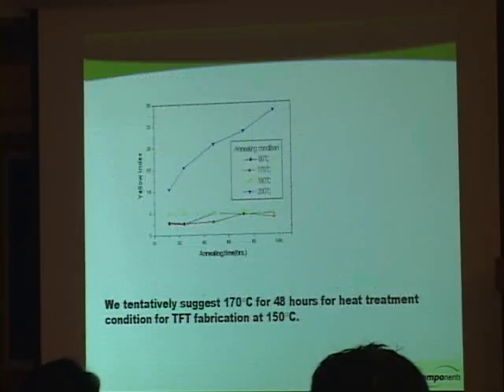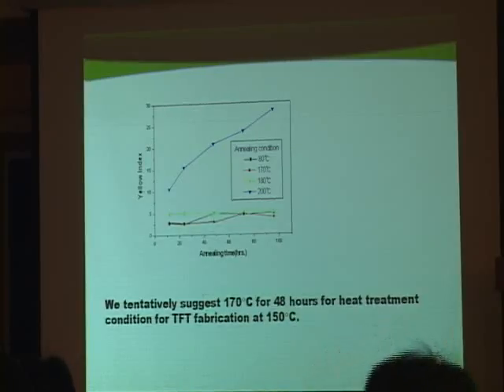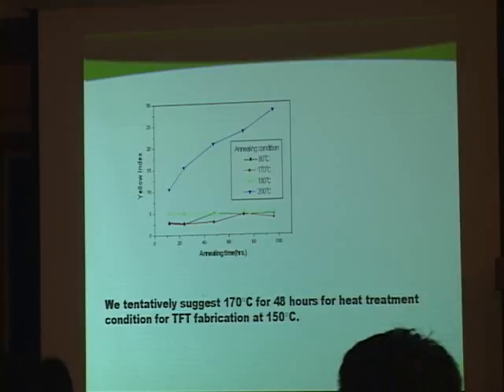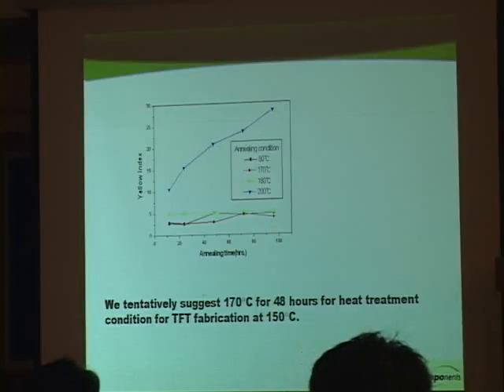But one of the problems developed during this is that the yellow index increases at a 200 degrees C temperature. That's a big setback for us. There are a couple of reasons why this yellow index increases for the PS. PS itself is not that much affected. However, some of the additives inside the film, as well as the coating that goes on, are not stable enough. I mean, mechanically, dimensionally, it's stable, but optically it changes. So the problem occurs. So now we suggest 170 degrees C for 48 hours, which is quite comparable to 200 degrees C heat treatment. So we suggest 170 degrees C for 48 hours for TFT fabrication at 150 degrees C.